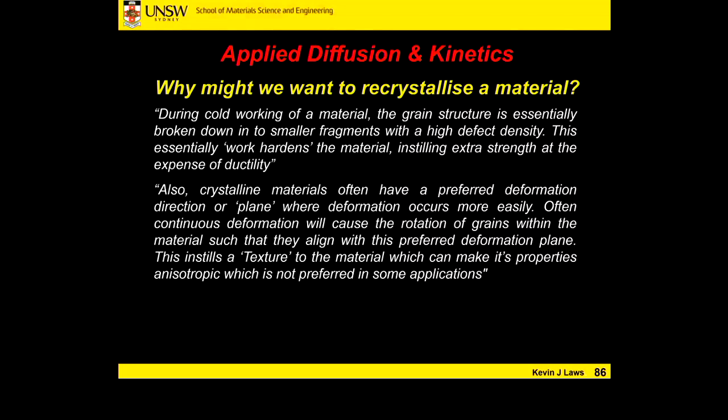In a polycrystalline material, this becomes irrelevant because all the grains are lined up in random directions, so everything evens out, becomes an averaging effect. But after we roll it, and all the grains are now lined up in the same crystallographic orientation, we end up with a sheet material that might be stronger or allow more deformation or ductility in one direction compared to another. That's what texture is. So it can be a big problem, or we can use it in industry.